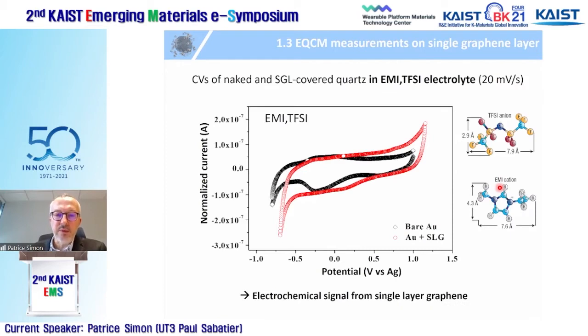Then what we did was to make a cyclic voltammetry using this SLG coated quartz, single graphene layer quartz, in an electrolyte. The electrolyte is ethyl methyl imidazolium TFSI salt, which is an ionic liquid with no solvent in the first step. And this is a cyclic voltammetry in black of a neat quartz, and in red of a quartz coated with SLG. So as you can see, your cyclic voltammetry shows a typical feature of a capacitive double layer. There is no redox peak. So in red, we recovered the electrochemical signature of a single layer graphene.